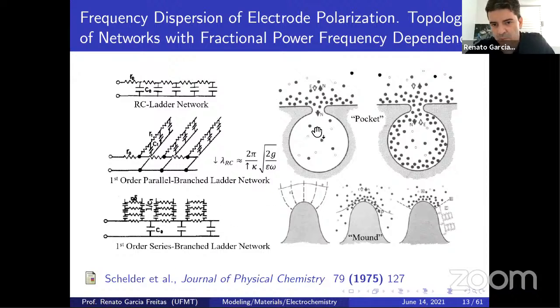So suppose that we have a pore, a pocket, with an electric field down here, like E, the electric field line. We have a small advantage of flux of species in here. As soon as we increase the voltage, we increase the species. If we have a lot of species here, we have the Coulomb law and the interaction of these species, and the electric field itself becomes opposite. So we have the flux of species that get inside the pores and get outside the pores in a pocket one. However, in the mound, we have other terms, like the power of peaks.